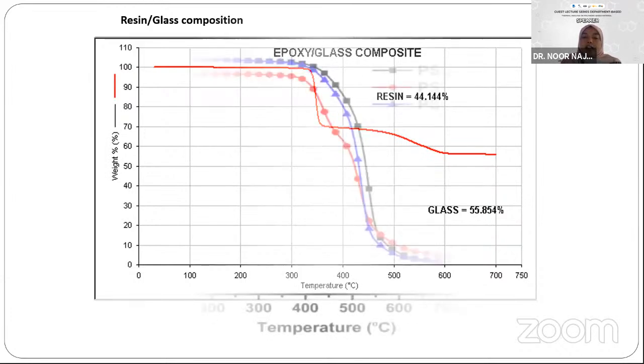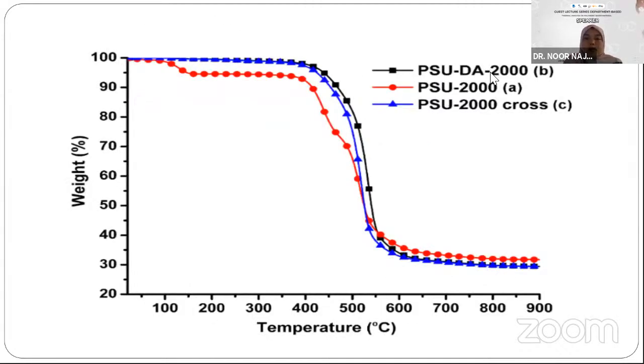Okay, so this one is the same sample with different types of fillers. PSU represents the polymer and you add fillers inside. Different additions of fillers will give you different degradation curves, like PSU 2000, which degrades earlier compared to PSU DA 2000 and PSU 2000 cross C. So that is what you can highlight in the analysis of TGA, thermal analysis.